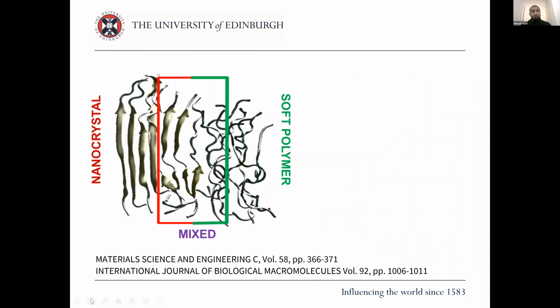Now, whilst modeling the internal structures of silk, one of the discoveries that we made through the modeling, which has led on to this hypothesis that we need to test experimentally, is that semi-crystalline regions form at the interface between nanocrystals and amorphous matter. And this seems logical, actually, from an energetic perspective, because you've got the amorphous matter that's basically crumbling and the stiff matter that's trying to hold itself up. So logically, at the interface, it makes sense that it would form semi-crystalline regions.